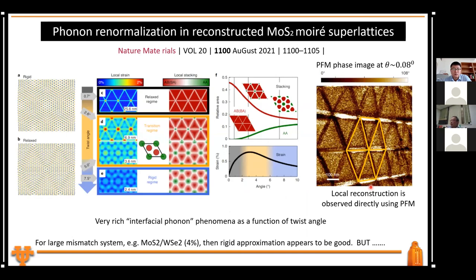Right. Then later on, we applied this PFM. This was done primarily by my colleague, KF Lai, to also measure this moiré pattern when they are on an insulator. And Elaine used this technique to end up looking at very interesting interface phonon and see this beautiful phonon renormalization. And since this is her work, I won't say much, I'm only happy to be part of it, okay?